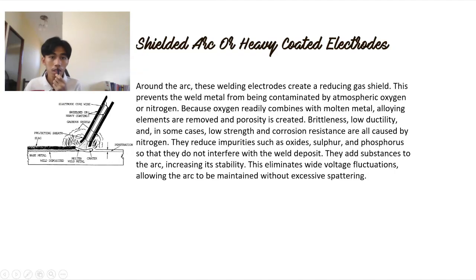So, for a shielded arc or heavy coated electrode, around the arc, This welding electrode creates a reducing gas shield. This prevents the weld metal from being contaminated by atmospheric oxygen or nitrogen. Because oxygen readily combines with molten metal, alloying elements are removed and porosity is created. Brittleness, low ductility, and in some cases low strength and corrosion resistance are all caused by nitrogen.